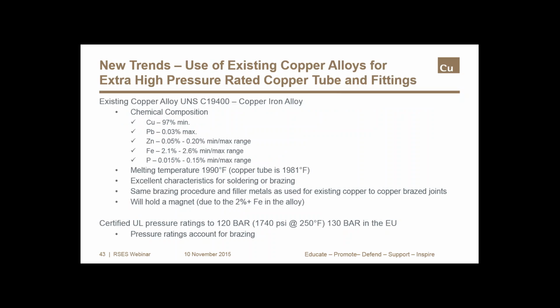So let's turn our attention now to a copper alloy, alloy C194, that's now being used to produce tube for extra high pressure applications. If we look at the composition, that 2 to 2.5% of iron in this alloy is really what gives it the strength to handle working pressures of over 1,700 PSI. And that pressure rating is UL certified.